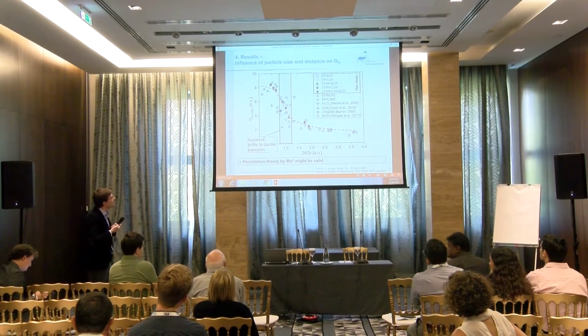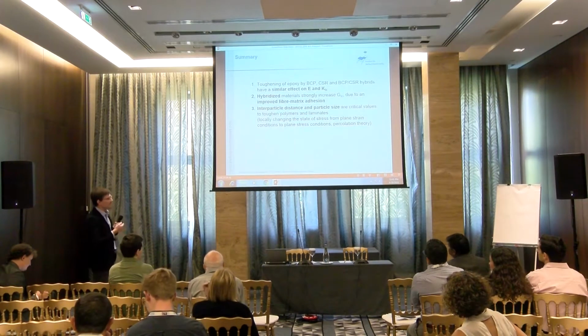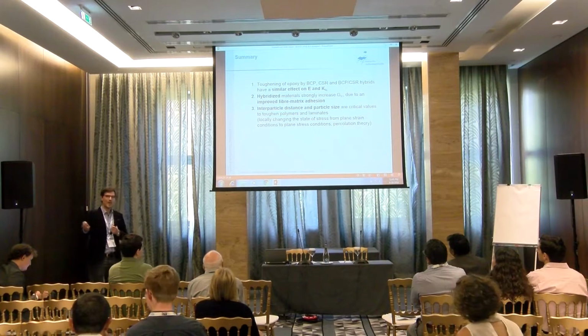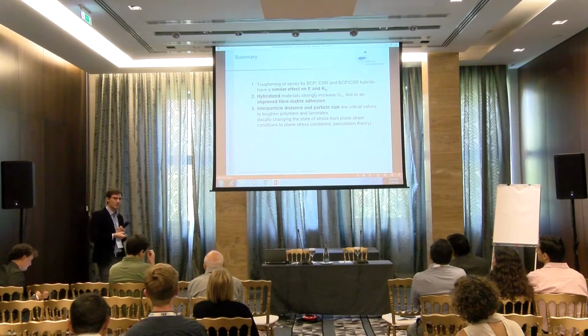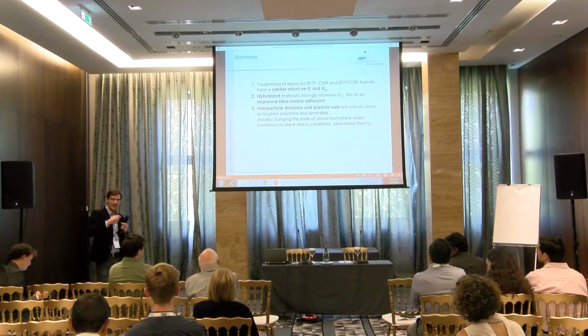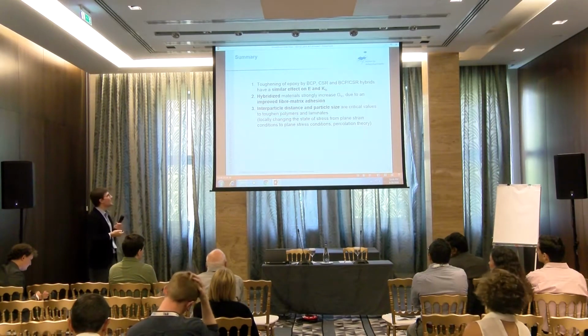So what you see here is a kind of apparent brittle to ductile transition. What we can make out of that is you only need to add more and more particles into your system, which is already possible now by using master batches, and you can activate your matrix rather than it only being a carrier for your particles, right?